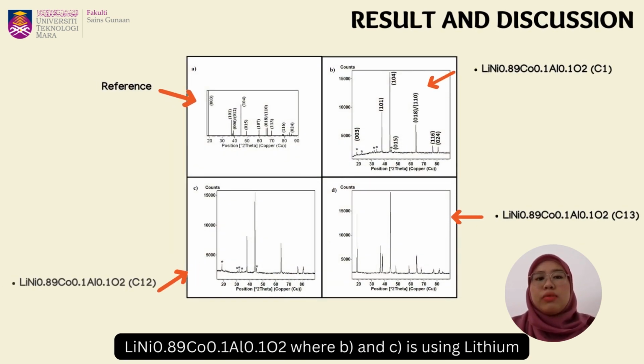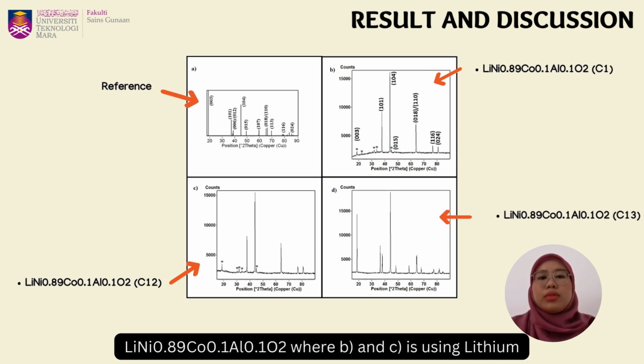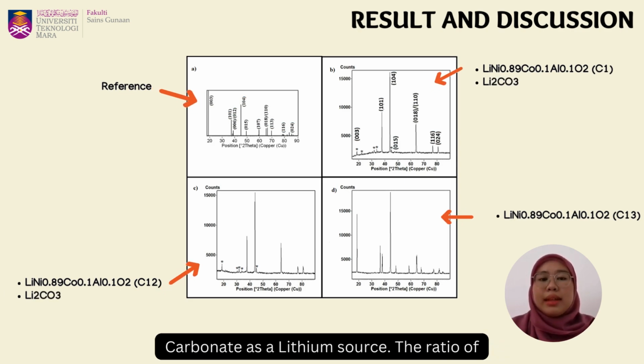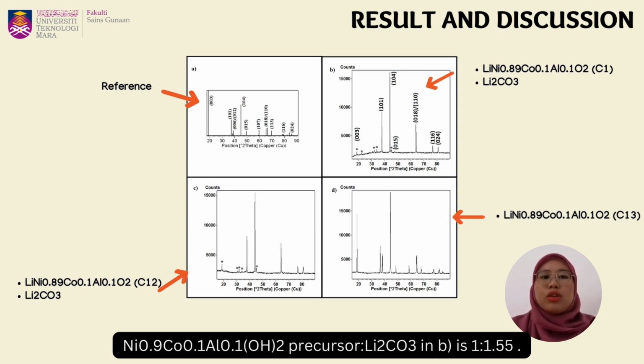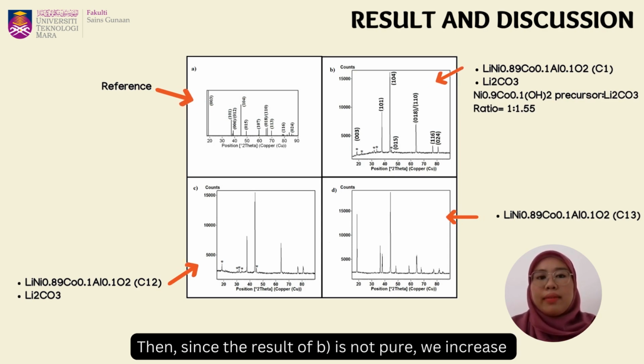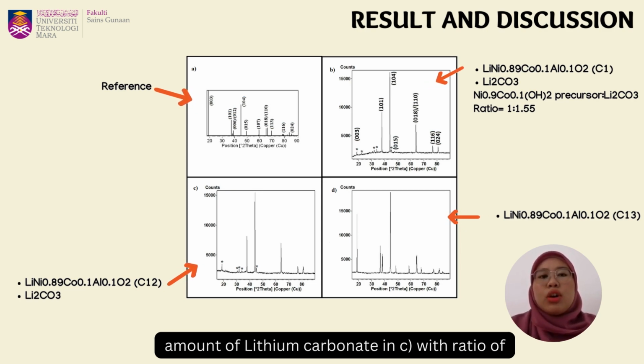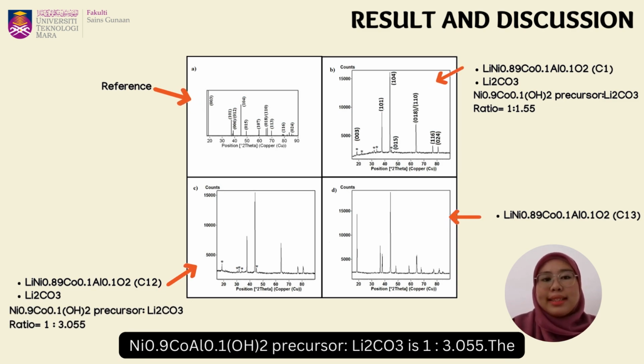The figure shows the result of XRD of nickel-rich lithium nickel cobalt aluminum oxide, where B and C are using lithium carbonate as a lithium source. The ratio of nickel cobalt aluminum hydroxide precursor to lithium carbonate in B is 1 to 1.55. Then, since the result of B is not pure, we increase the amount of lithium carbonate in C, with a ratio of nickel cobalt aluminum hydroxide precursor to lithium carbonate of 1 to 3.055.